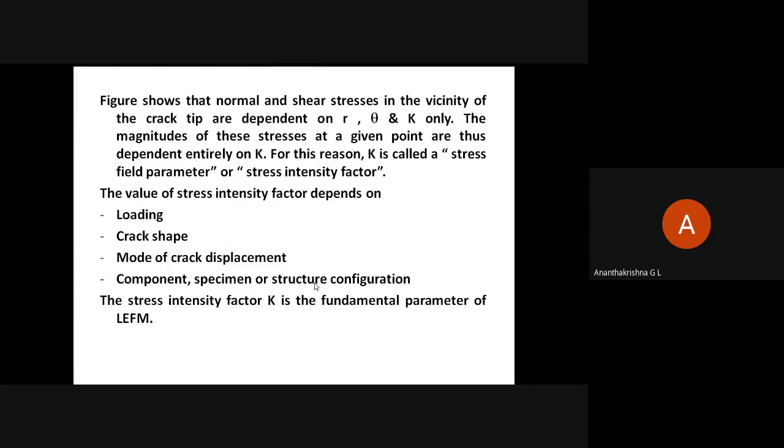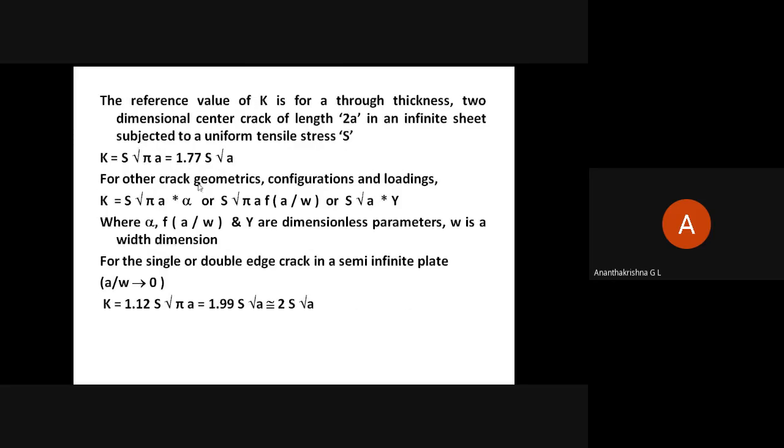The reference value of K for a through thickness crack of length 2a in an infinite sheet subjected to tensile stress is given by S root pi a. This is what we have seen in the previous slide also. For root pi, he has taken it out, so the stress intensity factor can be written as 1.77 into stress into root of crack length.